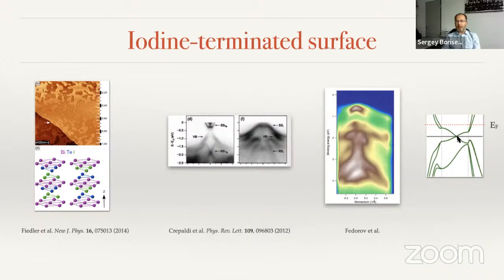What we notice is that it was also established earlier that there are two terminations in this material, tellurium termination and iodine termination. You cannot get an ideal single crystal in ARPES, because when you cleave, you have either one or the other.